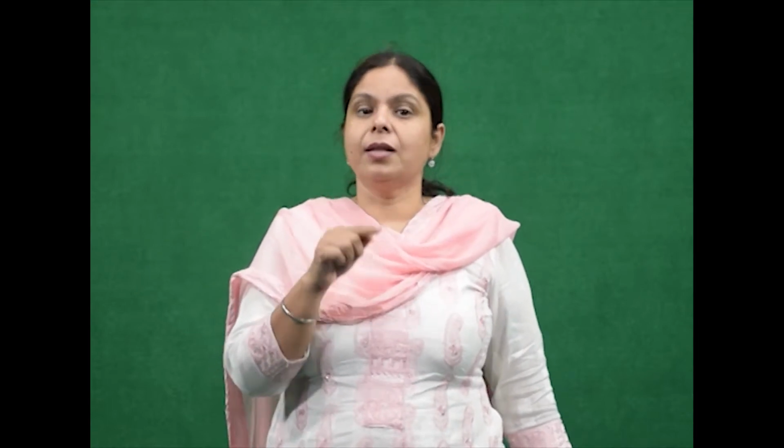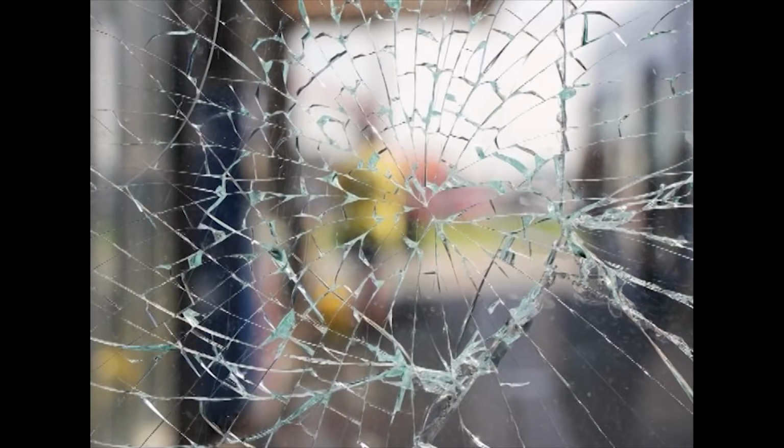So, when the glass breaks due to tensile failure, the fracture is initiated on the side facing the force. The curved rib marks or the conchoidal marks will now meet the side facing the force at almost right angles. Then comes the hackle markings.